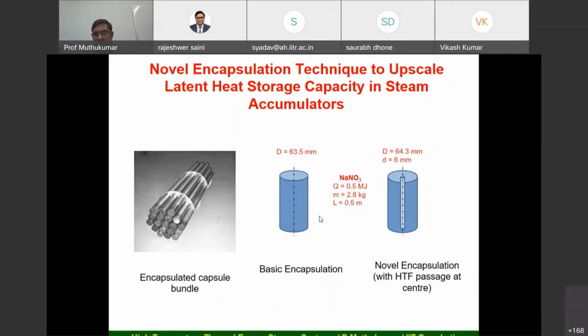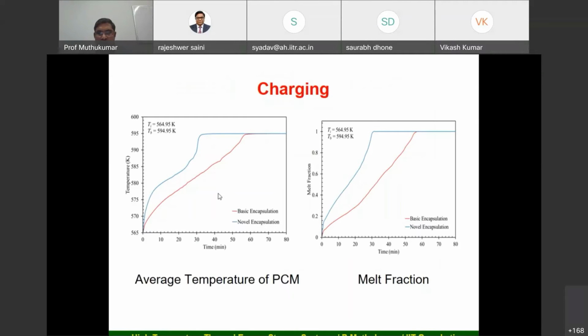Here the diameter of this capsule is about 63.5 mm. The salt we have taken is sodium nitrate. The amount of heat stored is about 0.5 megajoule, and this is our proposed novel encapsulation capsule. Here, what we have done is we inserted a quarter-inch tube. In both cases, we fill the same amount of material. Since we inserted one small tube here, the diameter increased slightly, less than 1 mm.